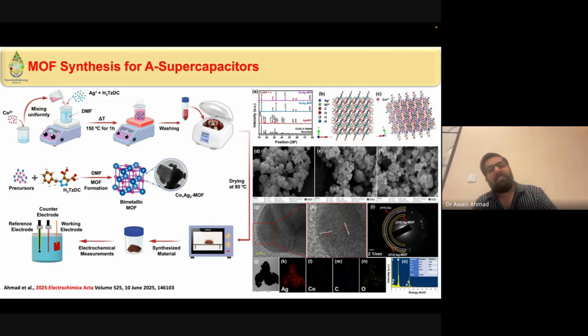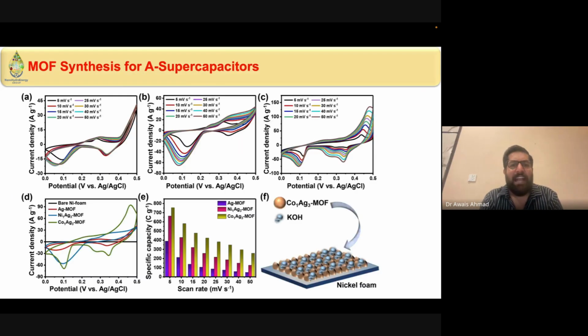Now, previously, I showed you a symmetric supercapacitor. Here you can see an asymmetric supercapacitor. You can see here the asymmetric supercapacitor behavior, which we checked with our electrode, and at the end we get more than 92% supercapacitor activity on the nickel foam.